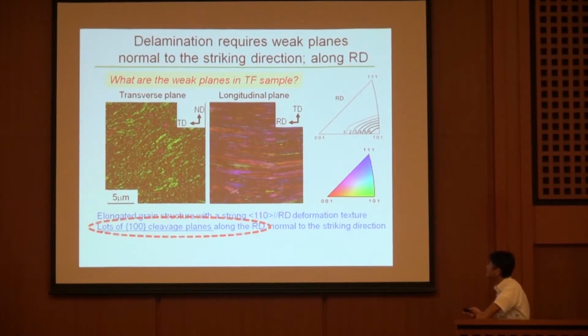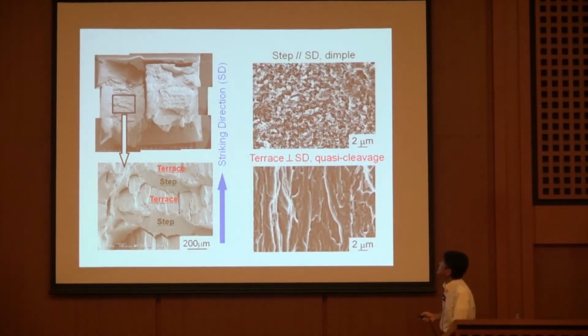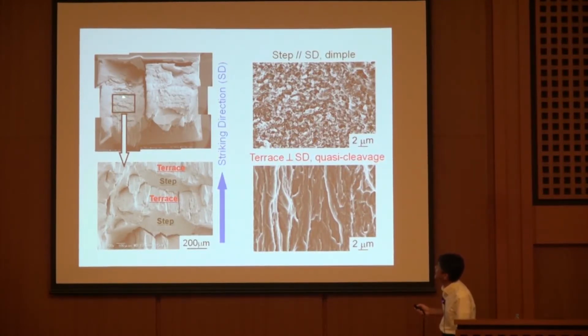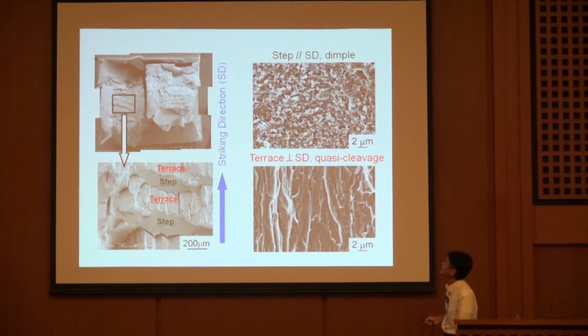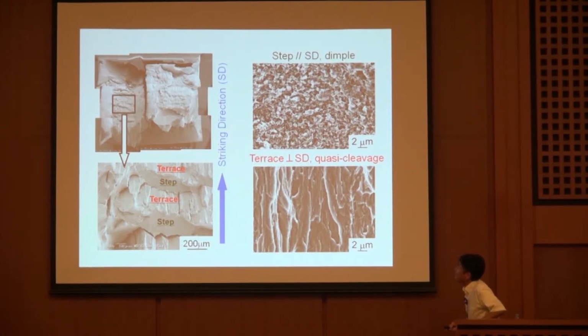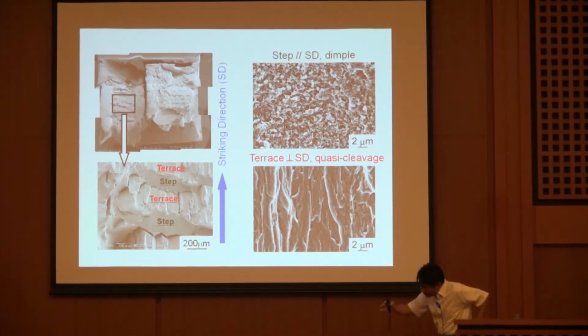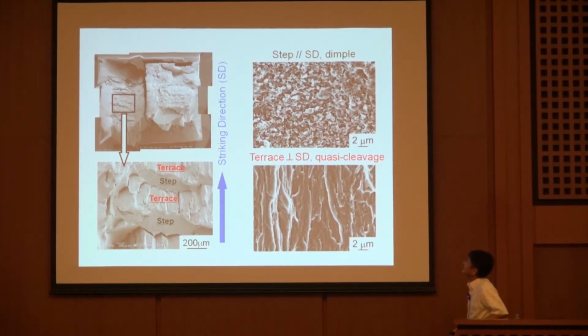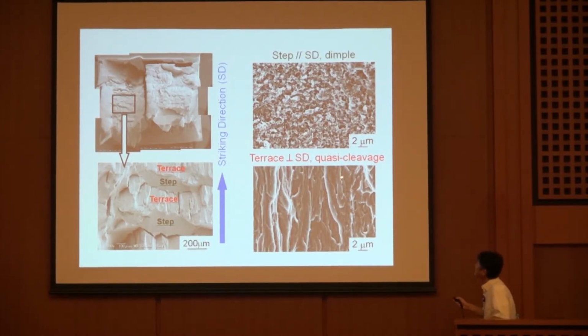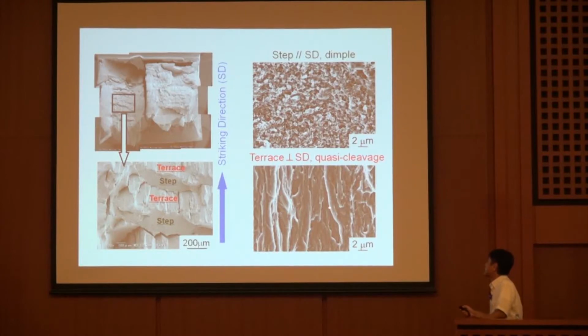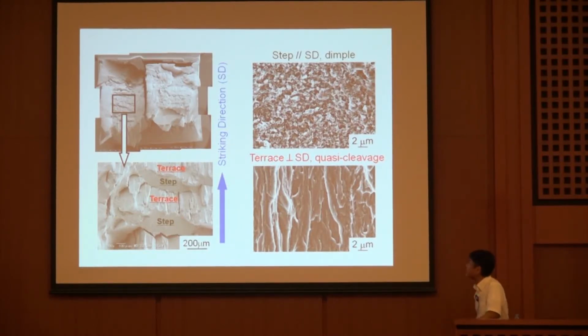To check it, we observed the fractography. Fractography shows some zigzag features, step and terrace, step and terrace. Step and terrace are parallel to the rolling direction, which is the longitudinal direction of the sample. And the step plane is parallel to the crack advancing or striking direction. On the step, you can see dimples like this. However, on the terrace, a precise cleavage fracture mode has been observed. It looks like cleavage fracture on the 100. So we believe the 100 cleavage fracture causes the delamination fracture in this sample.